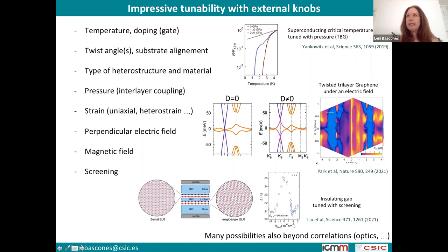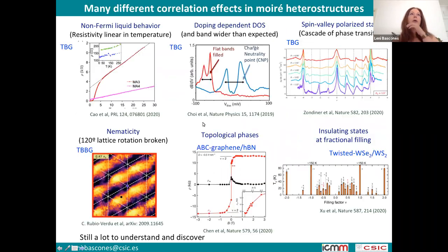Well, with so many possibilities, people are really observing a lot of effects. Just to give you an example, it's not only this insulating state that people observe, or only the superconductivity. Even if you are in the metallic state, there are clear correlation effects. For example, it has been observed that the resistivity is linear in temperature, similar to what I mentioned before in the cuprates. There is a doping-dependent density of states.